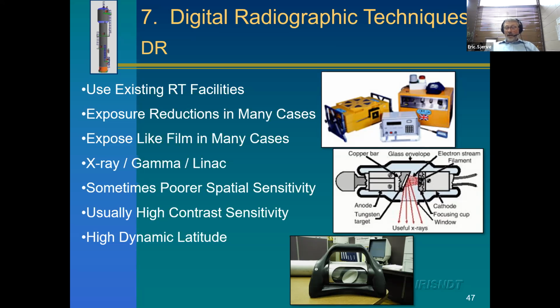And dynamic latitude is the ability to see many different thicknesses in the same radiograph. So we're far better than film with that. With film, if we have, say, a part of a casting that's small and thin and a part of a casting that's thick, we have to take two different radiographic exposures. With this technology, it's almost always one, and that's dynamic latitude. And then contrast sensitivity is the ability to see small changes in grayscale. And this technology is much better than film at that.